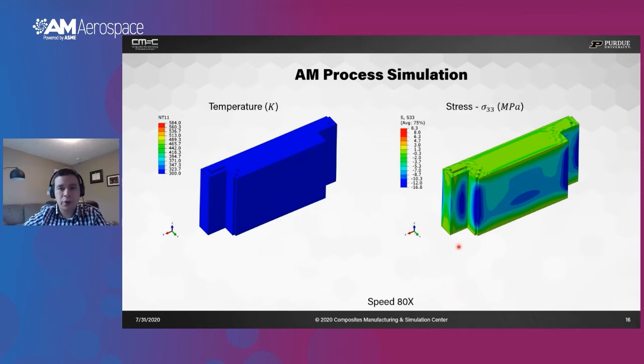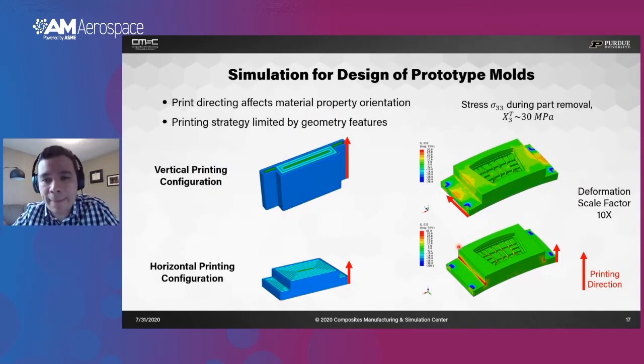So we will not focus on that, but rather on the effect of the different printing configurations. We can certainly print this part horizontally or in a vertical configuration. But since the direction that we use for printing the part affects how the material is oriented and what the properties of the printed material and the performance of the printed geometry are, we want to ensure that in the loading conditions that we have, both in molding as well as once we eject the part, we don't compromise the integrity of the tool.